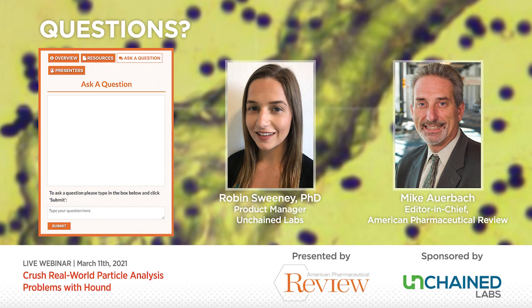For example, sometimes you care about particles within a certain size range if your API is only bioactive at a certain size. So in that case, you would do size-directed ID to say identify all particles that are 5 to 10 microns in size, or identify all particles that are over 100 microns.